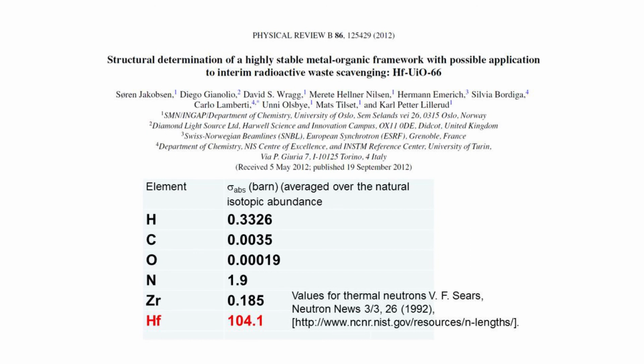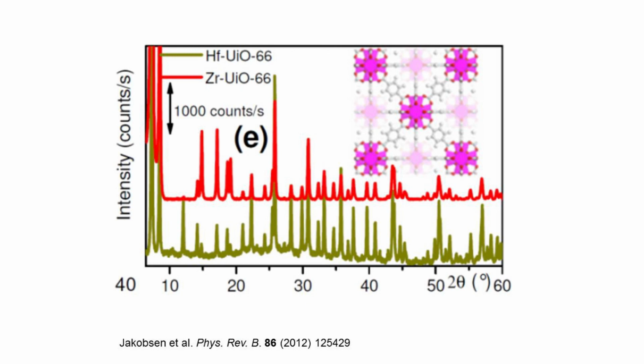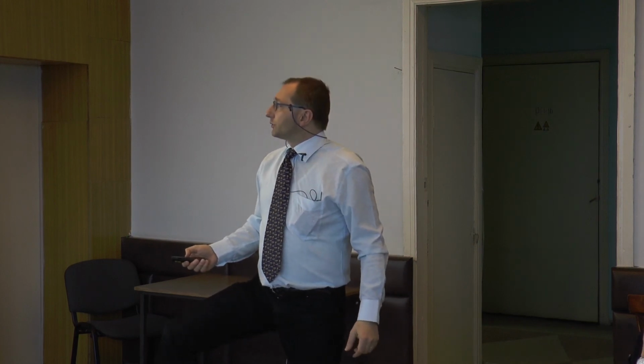But zeolites are limited by elements, so we have only low Z elements: oxygen, aluminum, and silicon. So this means that they are low X-ray and gamma absorbers, and they are not able to absorb neutrons. But the same holds for UiO-66. But if we change to hafnium, you can see that hafnium has a very strong absorption cross-section for neutrons. This means that if we are able to synthesize the hafnium homologue of this MOF, we can have a porous scavenging material where we can put inside our radioactive molecules, and that can be used itself as a partial shield for emission of gammas and neutrons. The material has been synthesized.